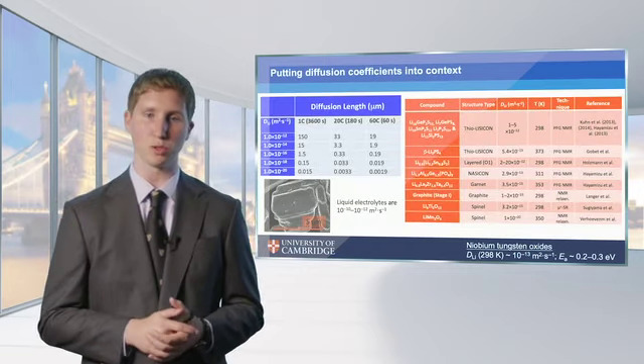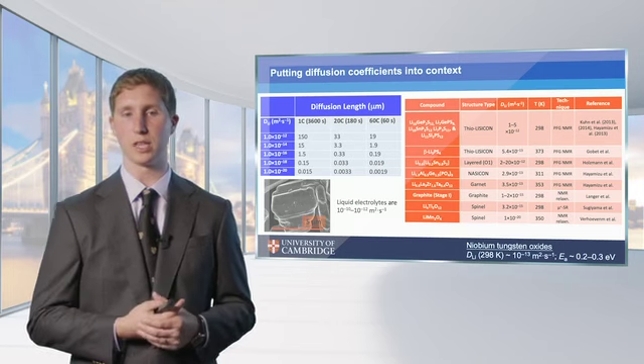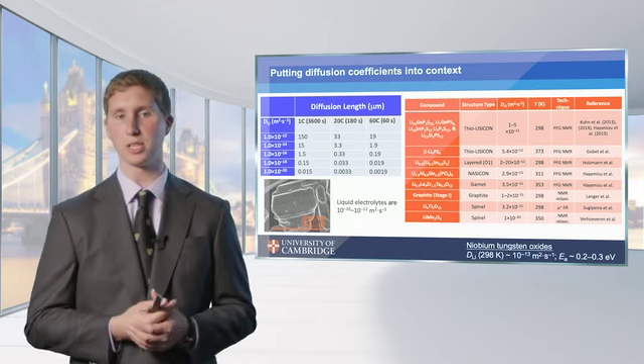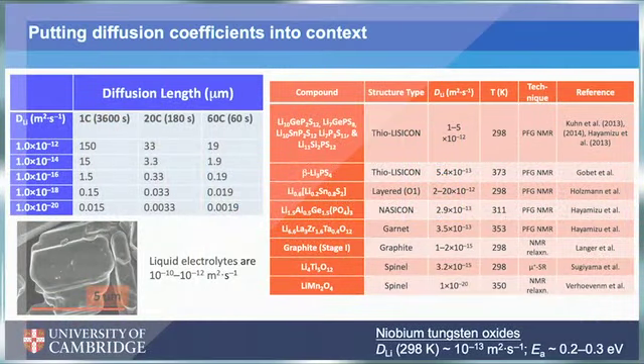Now, getting this information out was really useful to understand why we're able to lithiate these large particles in a small time scale, but we need to put these numbers into context. So what does it mean that we're at 10 to the minus 13 meters squared per second? Well, what it means is that we're only an order of magnitude or so off of the lithium diffusion in a liquid electrolyte. And similarly, we're about on par with the best lithium diffusion in single conducting solid electrolytes. And if we compare that to other electrode materials, things like graphite or LTO or some of the cathode materials, we're sort of 2 to up to sort of 6 or 7 orders of magnitude faster diffusion than you would see in common mixed ionic electronic conducting electrode materials.